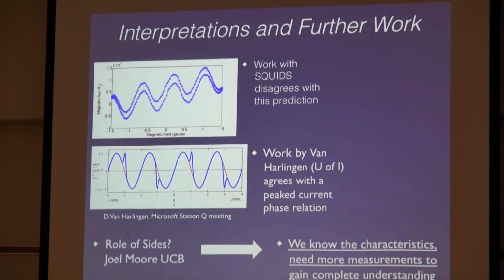we then looked at these samples with a SQUID, and we saw nothing interesting about the current phase relationship. Although I don't know, this is a DC measurement, and for reasons that have to do with quasi-particle poisoning, it might be that measuring these samples at DC or higher frequencies has an effect on what your current phase relationship will be. I should mention that more recent work by Dale Van Harlingen at University of Illinois has actually seen similar things to what we've seen and proposed similarly a peaked current phase relationship where every time you are at pi and 3 pi, you get a peak in the current phase relationship that's related to Majorana. But we don't know. We really need to understand a lot more.